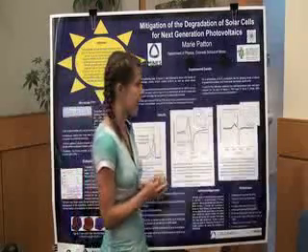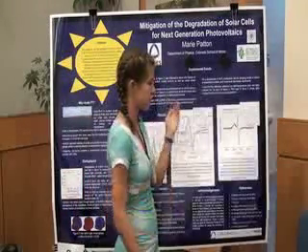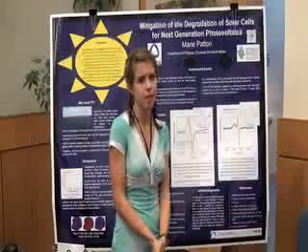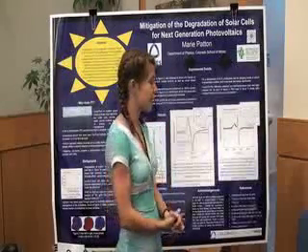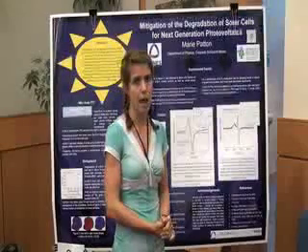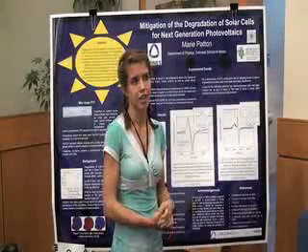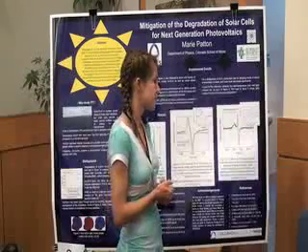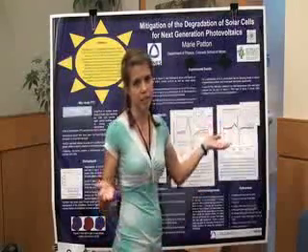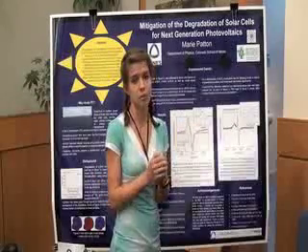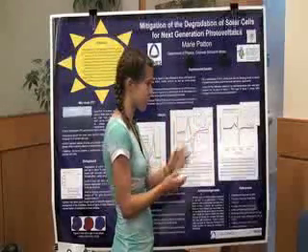The next thing I did was look at light-induced ESR. I did it at about 40 Kelvin, so I used liquid helium. I took a dark measurement, and then I shined an infrared laser on it, and then I took the difference. The fact that there's a difference between the dark and the light means that the photons were absorbed, and it actually changed the material.